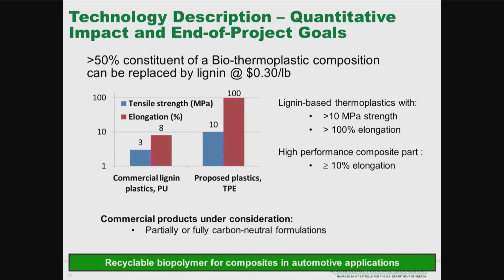So based on that, I would like to come back to our quantitative impact. What was our goal and where we stand on this particular project? We are assuming here all these formulations have more than 50% constituents of lignin, which is a plus point. So we can say that this is a partially carbon neutral product. And these biothermoplastic compositions with lignin, we are assuming the cost can be 30 cents per pound, since we are not seeking highly purified lignin.